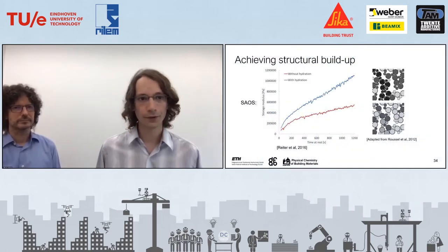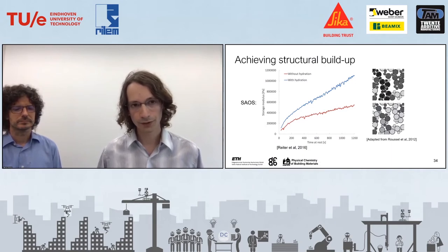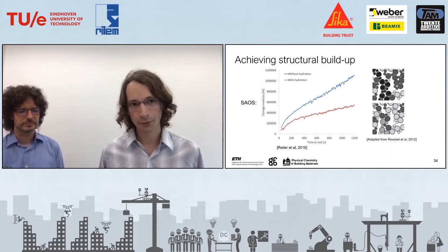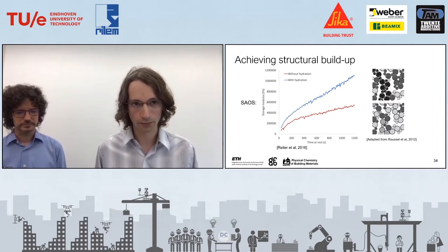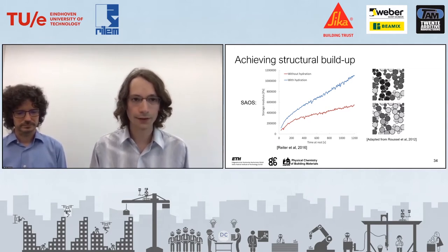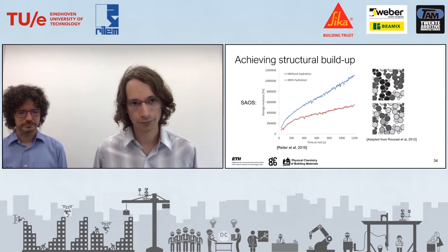If you can, you can go to slide 34. So this is where this is dealing with the subject. And the answer is, on the technical ground, we do small amplitude oscillatory strain. So basically probing the stiffness increase of the material non-destructively by plate-plate rheometry. And what we do in the first case without hydration is to strongly retard the cement hydration so that basically the hydration is not taking place. And in the other case, we let hydration occur.